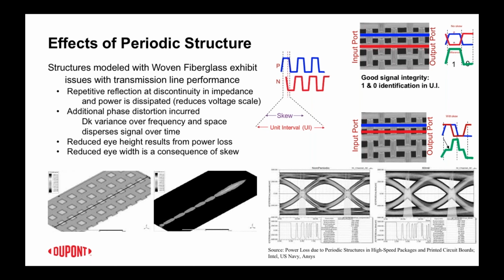Each of these is an opportunity for a slight reflection at the discontinuity in impedance, the slight impedance change that's going to happen as the transmission line goes over a yarn or is in between yarns, and it's got different impedance values in each of those locations. Each of those is an opportunity for some small dissipation of power as some of that signal tends to be reflected. In considering the skew part a little bit, there's some phase distortion that's also incurred at that point. So as you're going over regions of different dielectric constant by way of varying proportions of resin and fiberglass, there's some delay variance that happens, and that disperses the signal over time a little bit. The results are reduced eye height and eye width from some power loss and a little bit of skew that occurs along the way.